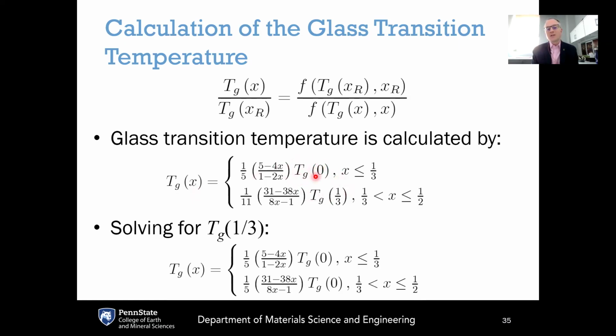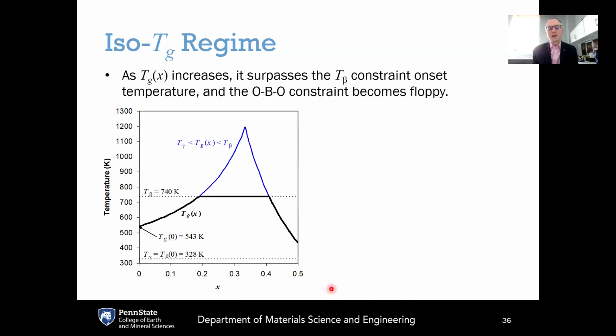And this is a piecewise function according to the random pair model, where in this regime it's relative to the Tg of the pure B2O3, and at this one it is the Tg of the 1/3 composition, which is the diborate composition. We can solve for Tg of 1/3 in terms of the original part of the piecewise function, since it has to be continuous, and then express the equation just in terms of a common reference point, Tg of 0. And if we plot that function, this shows the temperature that would be predicted here. This is Tg of 0, which is the measured glass transition temperature of pure B2O3. That is equal to 543 Kelvin.